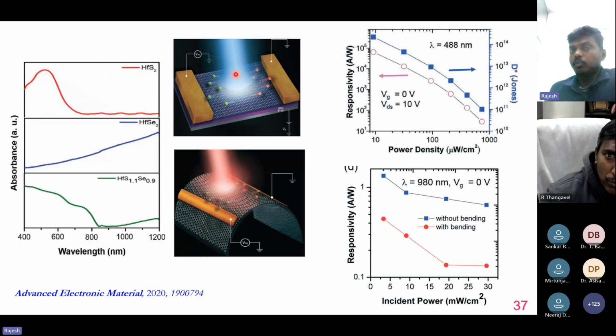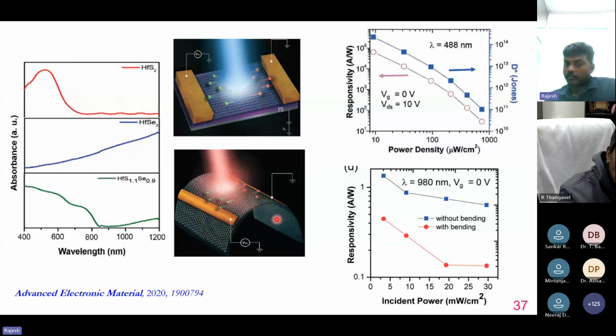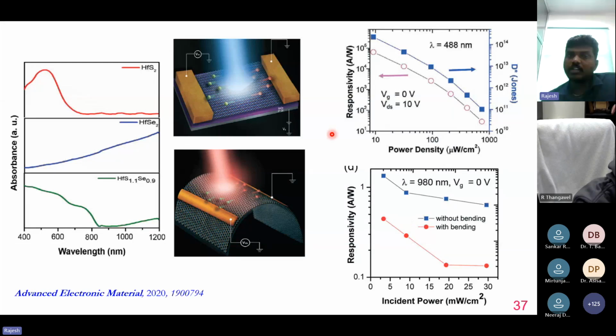In the case of the visible photodetector, we shine around 488 nanometer wavelength and are able to extract a very high photoresponsivity. In the case of near infrared, we shine a 980 nanometer laser on a flexible device. We also achieve a very good responsivity. So we proved hafnium sulfoselenide can act as both a visible and near infrared photodetector.